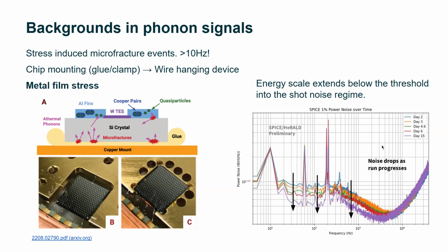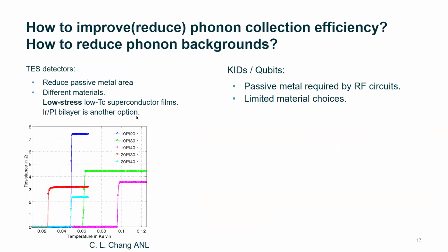On one hand, we can wait long enough until this decays away to achieve a better energy resolution. But on the other hand, the decay is quite slow. We do want to have something that is lower stress. So this is what we are doing right now with our collaborators at the Oak Ridge National Laboratory. We are looking into this iridium platinum bilayer material, which also offers us a low TC like the tungsten we are using, but also demonstrates much lower stress. So hopefully we can get a device with much less microfracture background in the TESs.